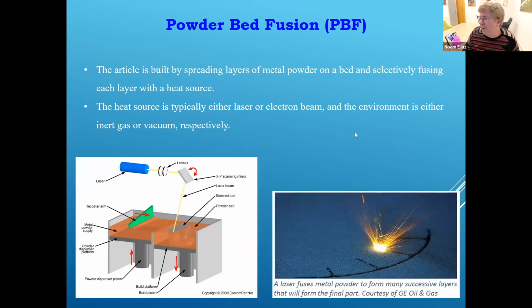When we think about the powder laser-based technologies, the powder bed fusion is significant, or one of the major ones, if not the major. So this is a schematic. On the left-hand side, you spread the powder and you come with an energy source, in this case, a laser. You heat locally the powder according to your file, and you lower the build platform, and this way you build the parts layer by layer. And on the right-hand side, you can see the sparkling from the interaction of the laser with the powder.